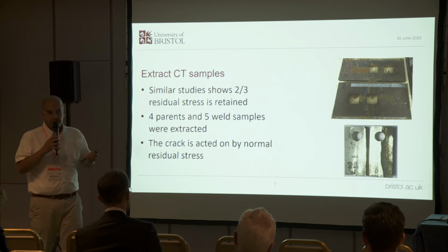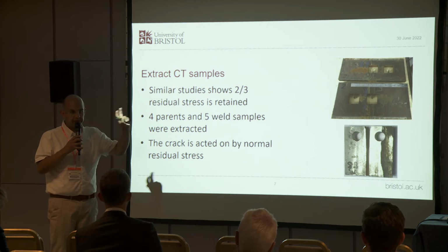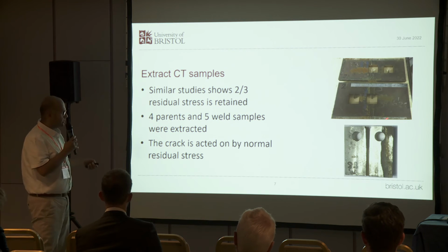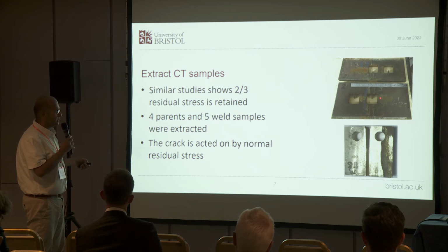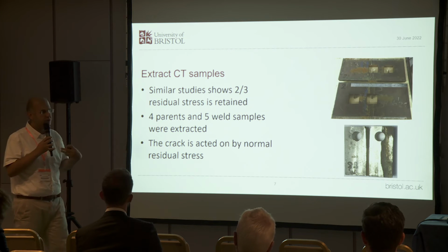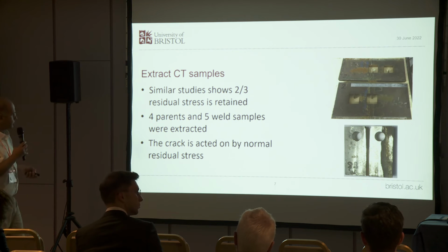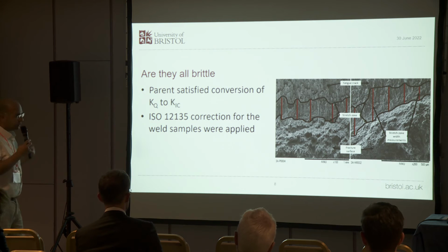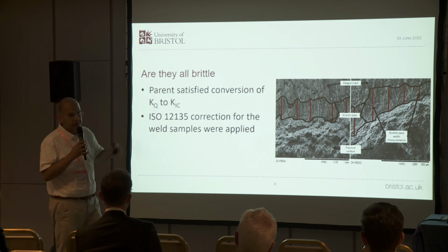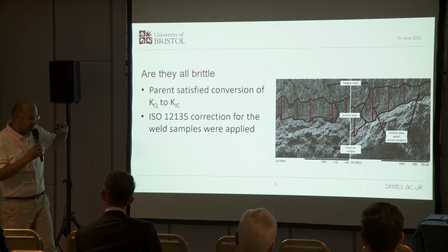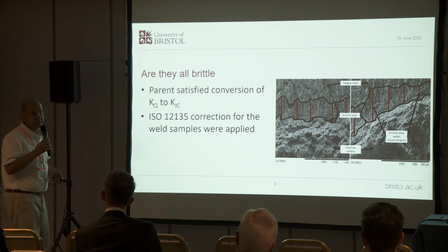And then we go and do some fracture tests. So we did variability of residual stress, we did the variability of the microstructure. Now we go and get variability in the fracture toughness of the material. Ferritic material, nice, relatively brittle. So you get loads of CT samples out of it. The weld is bang in the middle. You don't have to do an ASTM E1820 loading and unloading and all those things, because the crack propagation before it goes unstable is not that long.